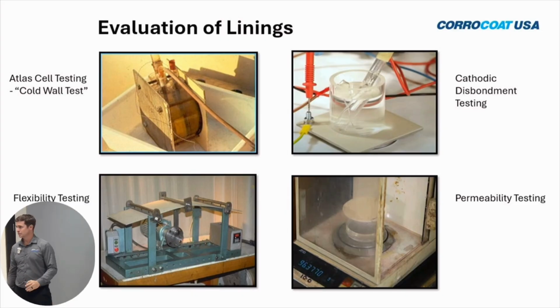Flexibility testing. Now, different materials, different resin systems, different glass flakes and loading have variations of flexibility. When you have a tank or a storage tank and in different areas, you want to at least have the coating to be as flexible as the steel. We can't do anything about steel that bends like this. Corrosion isn't your problem at that point. But we do understand that at varying thicknesses of coating, we have variable flexibility. It's not just about flexibility, it's about endurance.